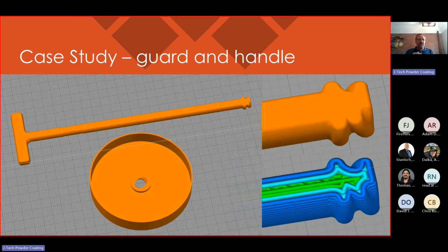So it was redesigned to print effectively with large format. So we targeted a 1 millimeter layer height. The big coarse 2-lobe tapered thread engages much easier than the fine original thread, holds a part very well. It's also tolerant to variations due to material shrinkage. We added flats on both sides of the handle so it can be printed laying down. And the grill slots were removed from the model, and they'll be handled with just infill to produce an equivalent free area.